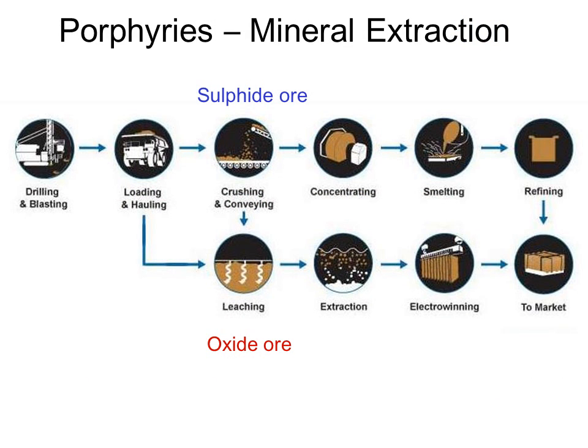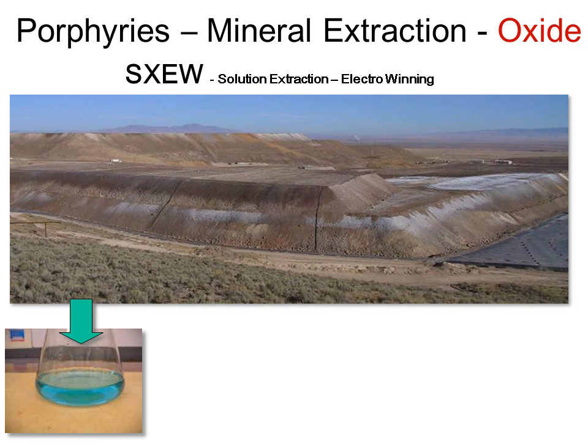Okay, returning to the overall process, that is the process for the sulfide ores, and the oxide ores, as I said, are treated differently. Direct from the pit, the oxide ore is piled onto large lined leach pads and sulfuric acid is applied. The top photo shows one of these leach pads with a new thick black plastic liner visible on the right of the pad. The copper oxide minerals are dissolved by the acid to give a blue copper-rich solution, mainly of copper sulfate.